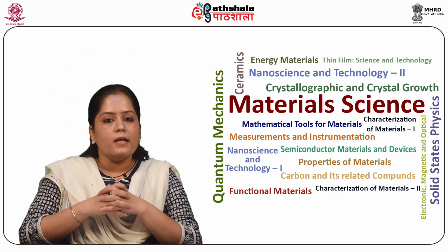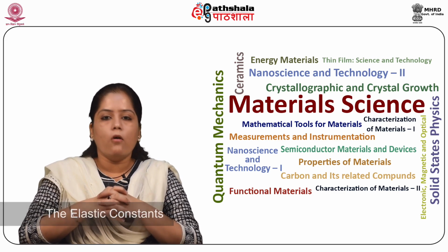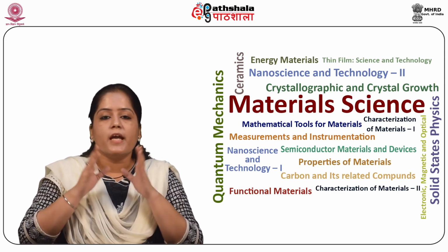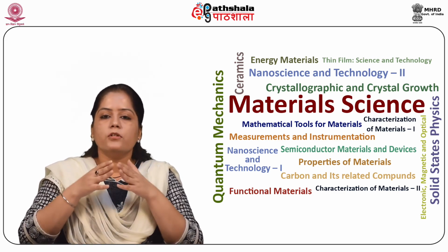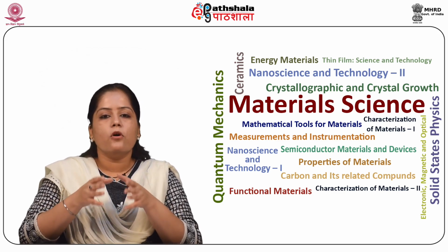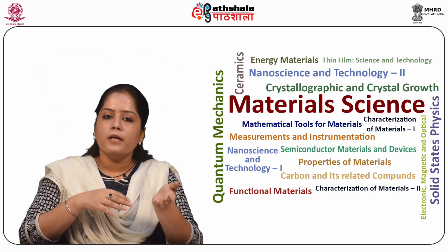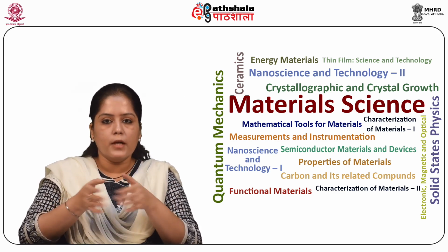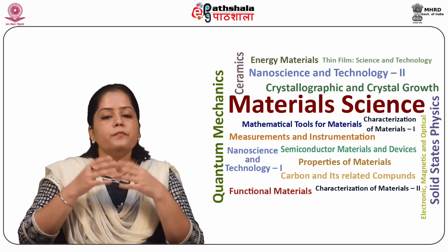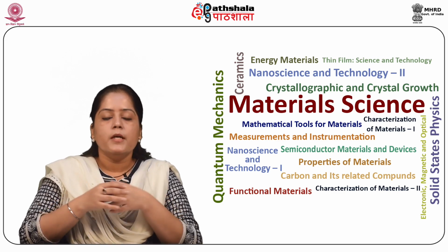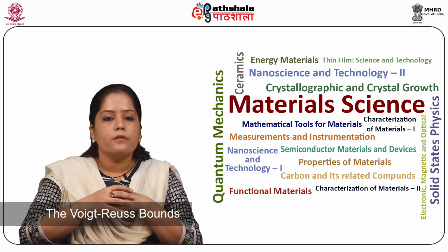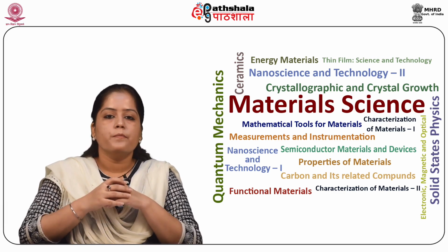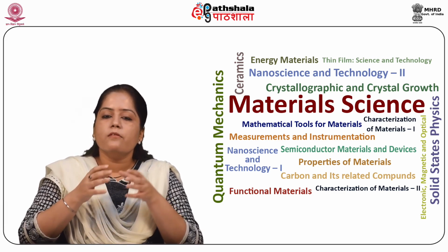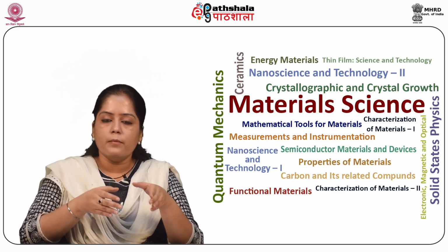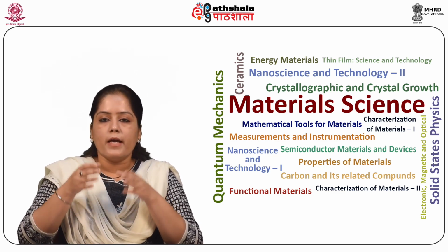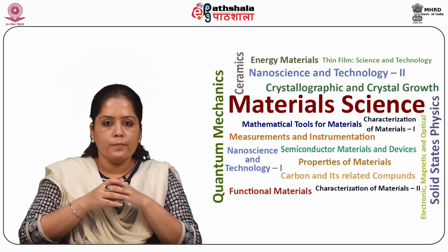Then we discussed that the elastic constants of the polycrystals can be predicted as for the composites using the rule of mixtures with the upper and the lower bounds of the bulk modulus B and the shear modulus mu being given by Voigt-Reuss bounds as follows, that is m equal to m1 v1 plus m2 v2 and 1 by m equal to v1 by m1 plus v2 by m2.